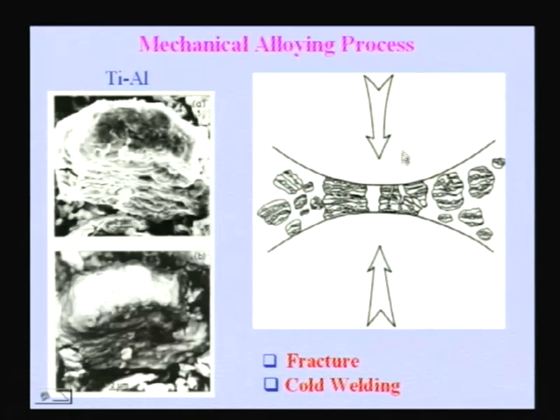This is a schematic diagram, and this is the actual picture of one such system. This is a titanium aluminum system where you can see a layered structure within one particle, and this layered structure, if you carefully observe in a backscattered image in SEM, shows you the white and black contrast, which clearly tells you the compositional contrast. White is one element and dark is another element. This comes because of the atomic number contrast. So whichever has a higher atomic number will look brighter.